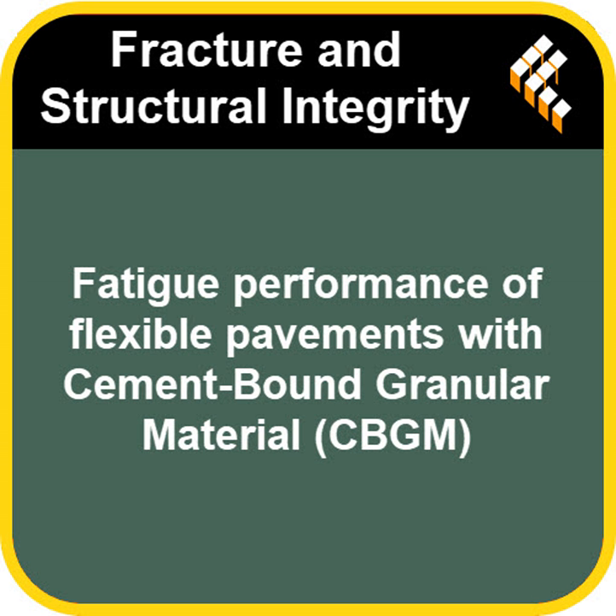And the results? You said earlier they were eye-opening. What did they find when they put these two fortune tellers, Dempsey and De Beer, to the test on these configurations? They are really staggering. For 3 of the configurations, types 1, 2, and 3, the Dempsey criterion predicted, well, instantaneous failure. Instantaneous, meaning zero life. Pretty much. What it means is that the calculated tensile stresses right at the bottom of the CBGM layer immediately exceeded the assumed flexural strengths, that very conservative 0.48 MPa value. So essentially zero fatigue life in terms of progressive damage under that construction traffic load. According to Dempsey, the road would crack almost immediately under the first few heavy trucks for these designs.